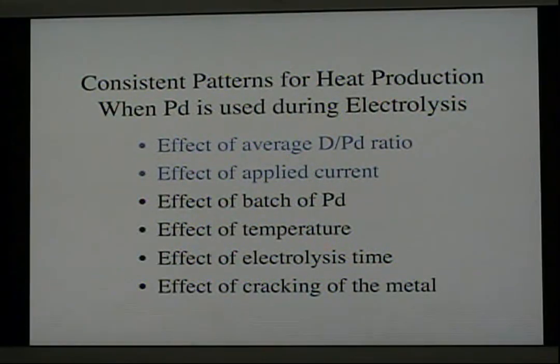People have found out that the batch of palladium is also very important. If one's lucky to obtain a batch of palladium that's active, then most pieces within that batch will produce excess power. On the other hand, if you're unlucky, which is most of the time, none of the pieces within that batch will produce excess energy.